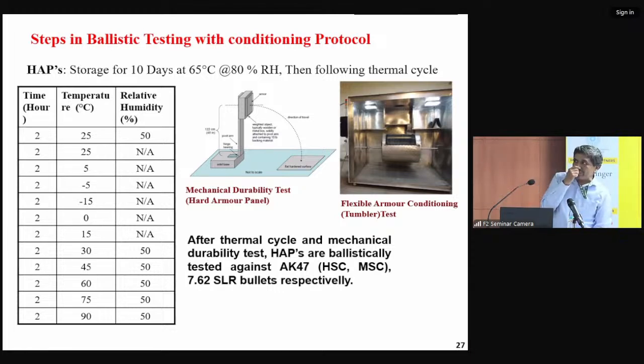You can see in the picture, this is the drop test equipment. Here, after taking the hard armor panel out at 90 degrees centigrade, it is dropped 2 times from a height of 122 centimeters, and then we do the X-ray. If that panel is found to have some type of cracks, the cracks will be identified in the X-ray, and the bullets will be intentionally fired over the cracks, because those cracks will be the weakest point.